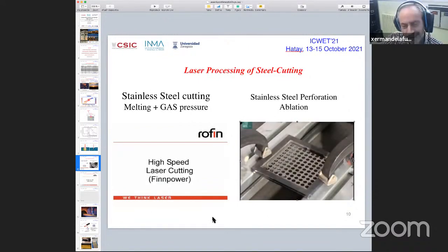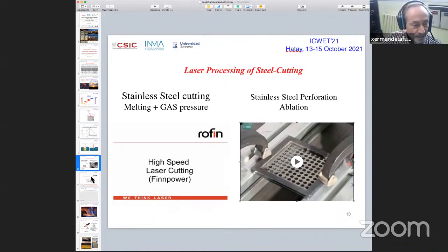And you can see this is 100 holes on stainless steel, about 1 millimeter thick. You can see how fast this is, the real speed. And that's the difference in the energetics when you use ablation, because ablation is related to plasma formation and shock waves, very intense shock waves. So the intense shock waves remove the metal that is being melted with this nanosecond pulse laser. We can go on to the next.